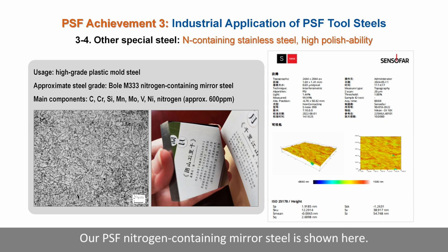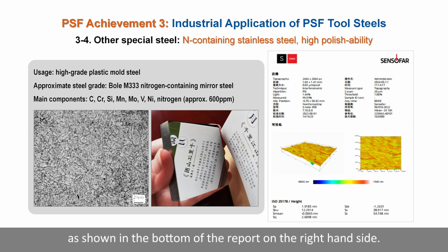Our PSF nitrogen-containing mirror steel is shown here. Its nitrogen is approximately 600 ppm. Surface roughness is polished to about 1.92 nanometers, as shown at the bottom of the report on the right-hand side.